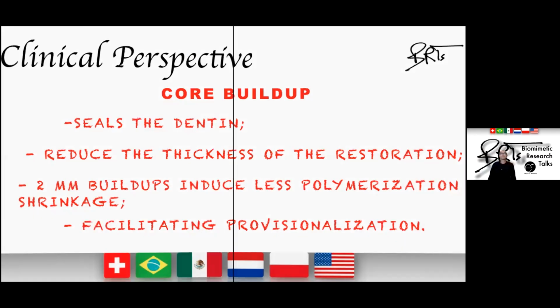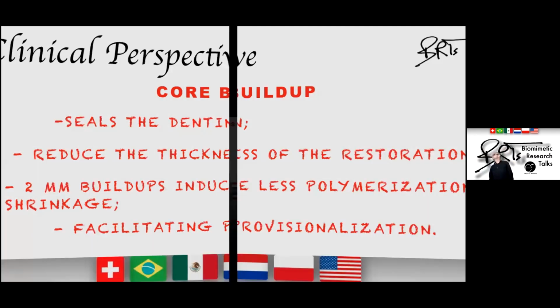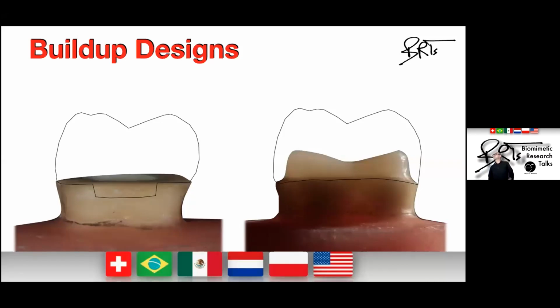In summary, we can conclude that the endocrown restoration is the least complicated way to restore endodontically treated molars without ferrule. And when we need to make a provisional, the 2 mm core build-up is the best way. I would like to emphasize that crown indication for Lava Ultimate, I mean nanoceramic resin, is no longer supported by 3M, and that other CAD/CAM materials should be considered for this indication.